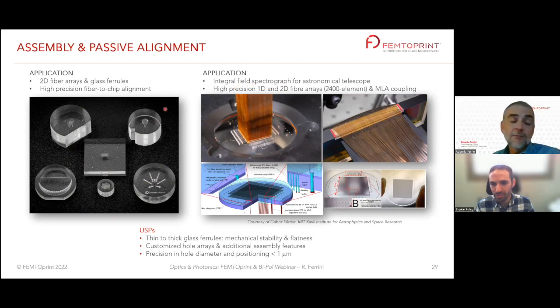This was a request from MIT. They wanted a fiber array system to create an imaging system for a spectrograph for an astronomical telescope. Here, what we did was first a V-groove with 2084 grooves to accommodate the fibers. The fibers were going down to a second plate that we made. It's a 2D hole array with 2084 holes to accommodate the fibers. Imagine the PhD who had to put all the fibers in.